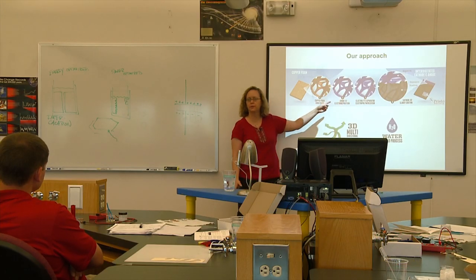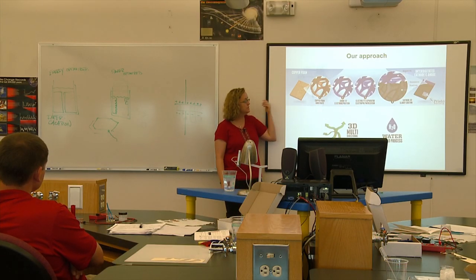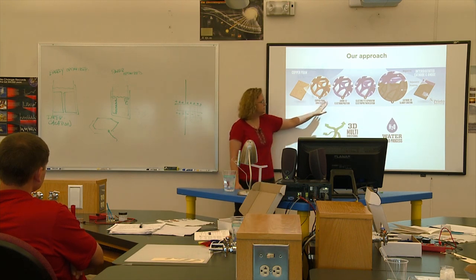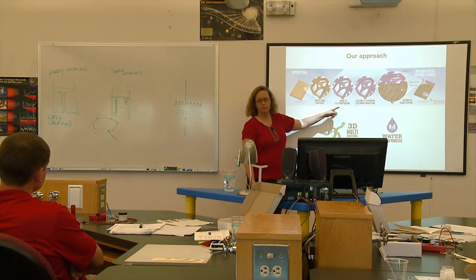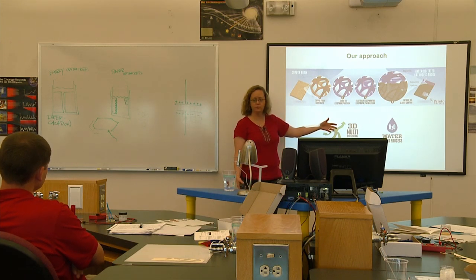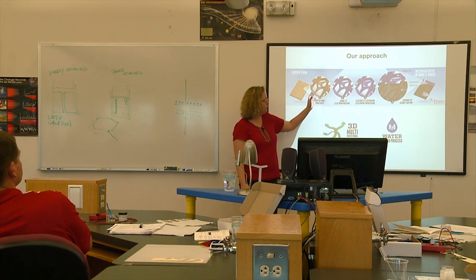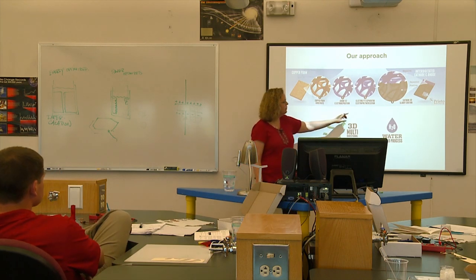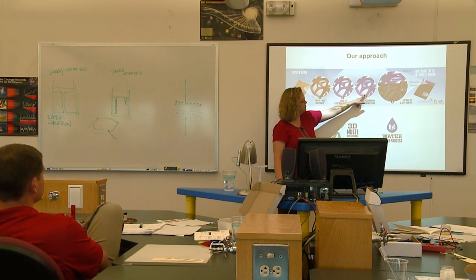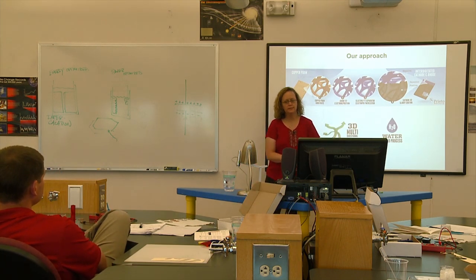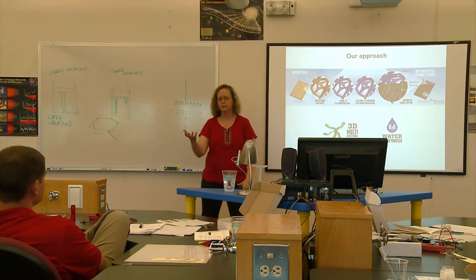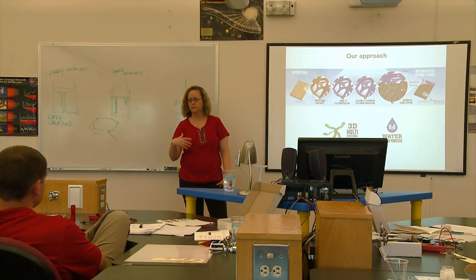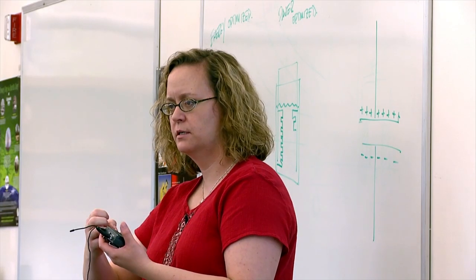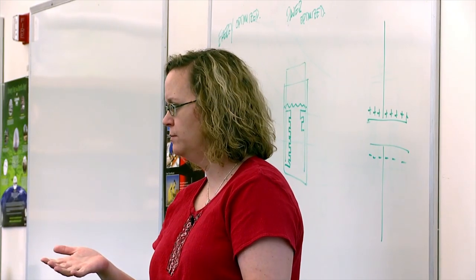And I'll tell you a lot more about what the anode is in a minute. It is actually purple, that's why I'm showing you it's purple. And then we take this, the anode we use is a really good metal, so we can still use it as an electrode. We put it in another water-based solution, and we coat it with a polymer electrolyte, that's this really thin layer. And then in the end, last step, we have a black ink that is our cathode material with some conductive additives. We drop it on top of the sponge, it gets sucked in, we dry it, and then that's our 3D battery.